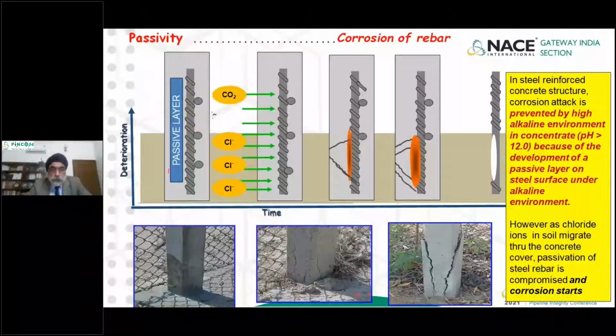Now, this slide basically gives you an idea of what I've been talking about, how the rebar corrodes. On the left-hand side is the first photograph, which is showing you a rebar. It is indicating a passive layer, which is built due to the cement around the rebar. Over a period of time, in the buried structure, chloride ions diffuse, and on the atmospheric side, if the structure is partly buried and partly in the atmosphere, carbon dioxide in the atmosphere diffuses into the concrete.